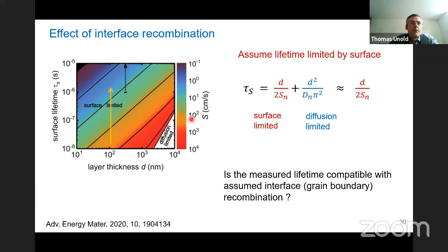And here's an overview plot where the layer thickness and the surface lifetime is shown. You can see that only for very thick devices, so this is basically crystalline silicon, diffusion limitation plays a role. So we can cross this out and live with this one. And that's really a very simple term now. It's the thickness divided by 2 times the surface recombination velocity. And with that, you can already conclude a lot of things.